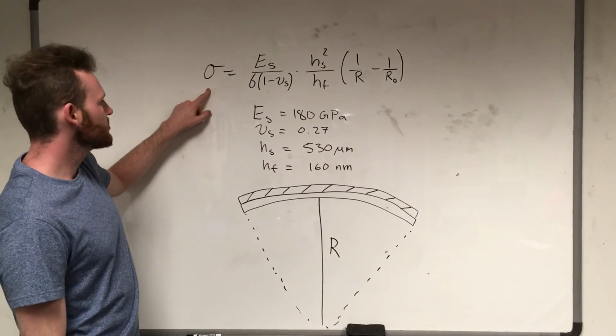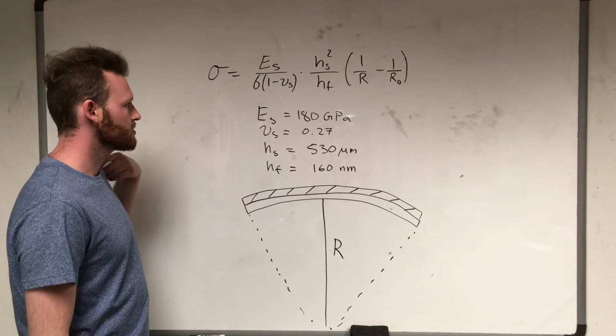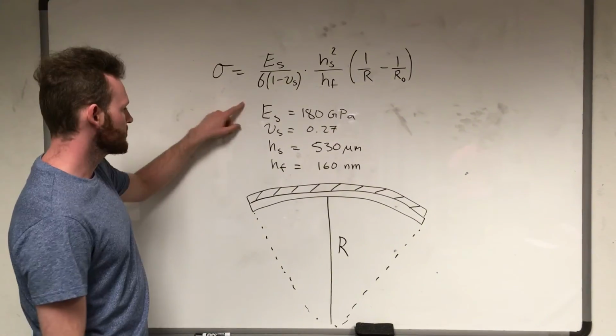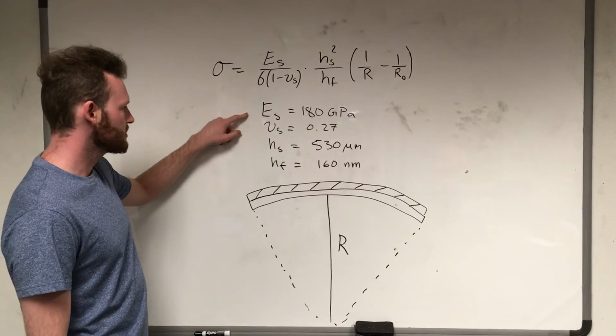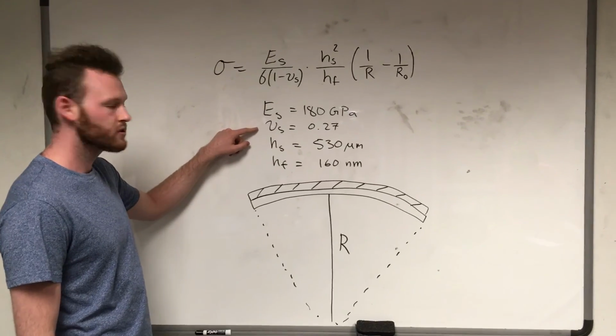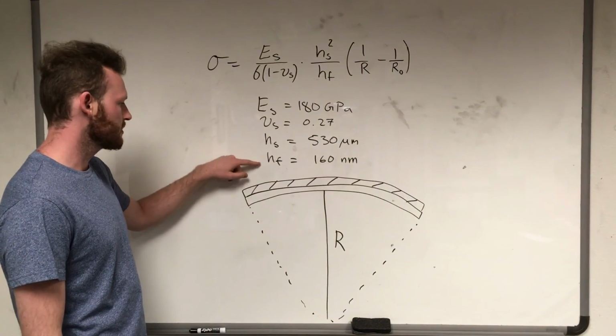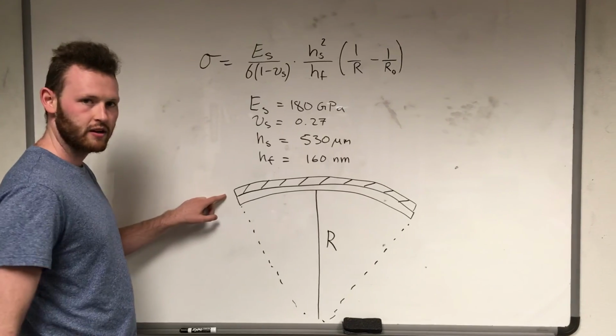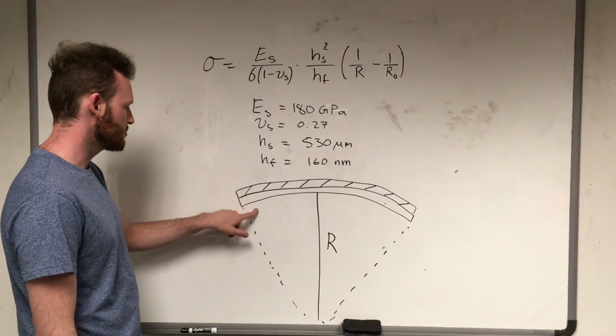This is the Stoney equation, which we use to calculate the stress induced in the substrate by the thin film. These are the values for our system: the Young's modulus of the substrate, the Poisson ratio of the substrate, the thickness of the substrate, and the thickness of the film. And here's a schematic of the substrate and the film.